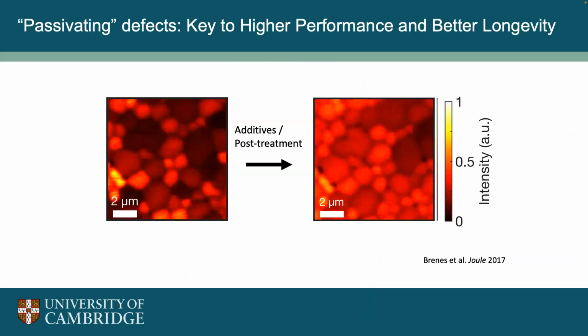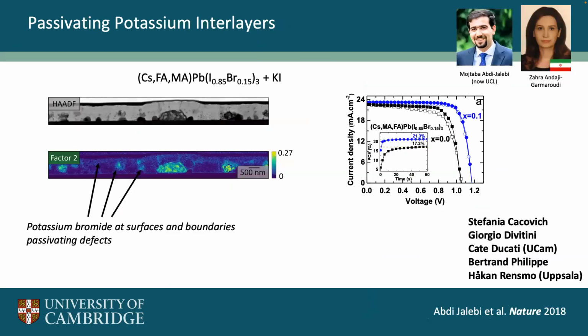Just some examples of where we've been able to heal some of these defects and these traps. So here we've been using different additives and post treatments to make these maps much more uniform. You can see that here, these dark grains have really brightened quite significantly, and this is promising again for processing much higher performing films.